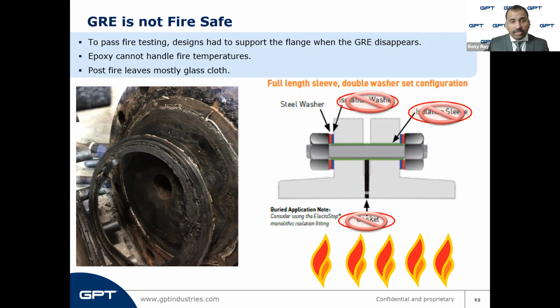The components that contribute to a loose flange assembly are the isolating washers and the isolating gaskets. So if you have isolating washers where one of them is 3.125 mm thick, and they fail on both sides in that thickness, and the gasket also fails, it can lead to leakage, and the media in the line can add more fuel to the external fire, leading to a catastrophe.